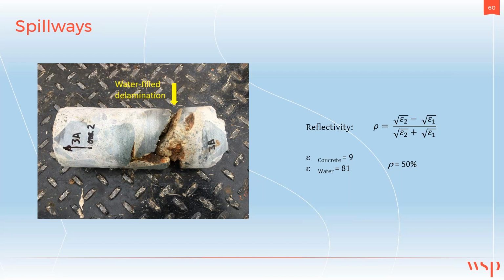The other thing is that a ground-coupled antenna should be either in direct contact with the ground or within a maximum of 10% of the wavelength, because that's when the greatest amount of energy is capable of transmitting through the substrate. So we have two issues working against us here: one is the reflectivity, and the other is that the delamination was too wide, even greater than 10% of the wavelength, so ground coupling was lost.